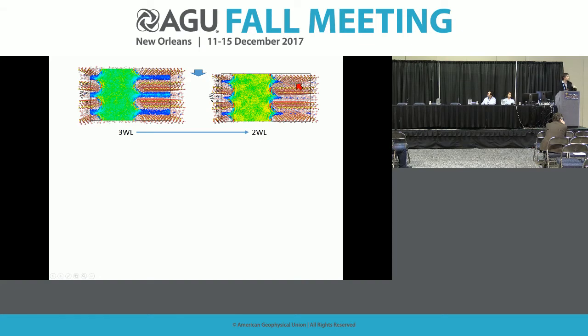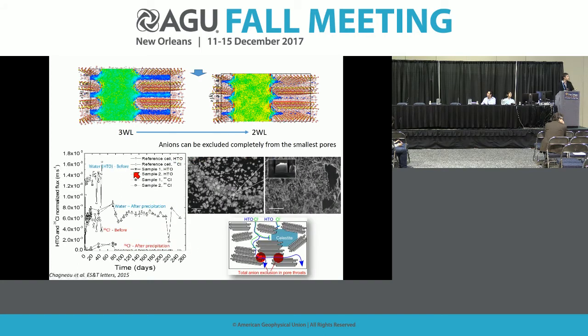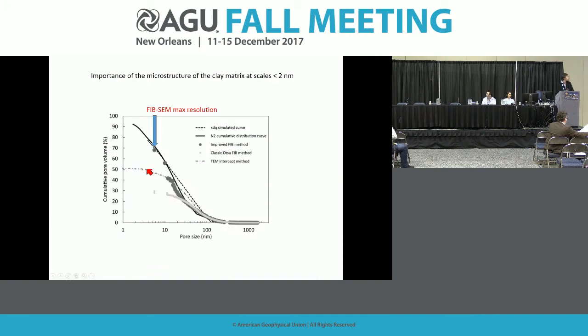But if you decrease the pore size again, like in a very deep clay formation, you will have, in fact, a complete exclusion of the pores to anions, meaning that only cations, water and neutral molecules can diffuse through this kind of pore. And this can also be seen from experiments. This experiment by Chagneau, 2015, is a very nice one showing that after the clogging of the big pores with mineral precipitation, you have a decrease of the water diffusivity, but a complete suppression of the chloride diffusivity. It means you have disrupted the diffusion pathway in the biggest pores, and then only the smallest pores can ensure the diffusion, but since they are not accessible to anions, the anions cannot diffuse anymore. So the microstructure of the clay matrix is important, scaled down to less than 2 nanometers, in fact.